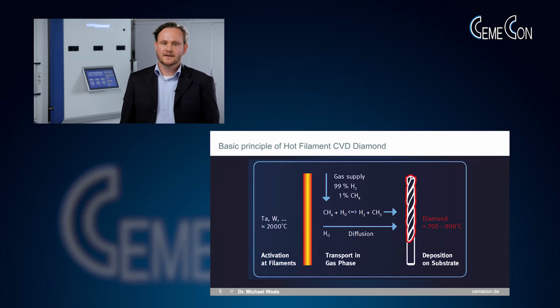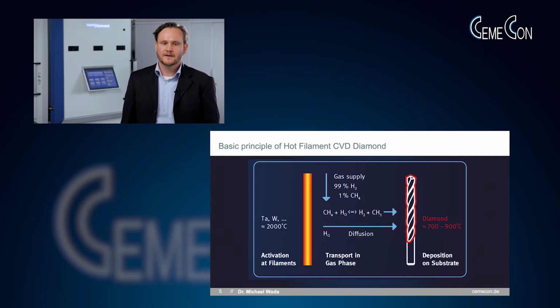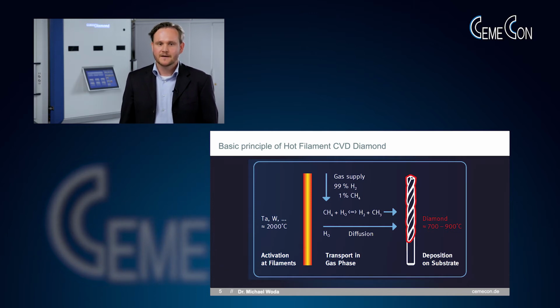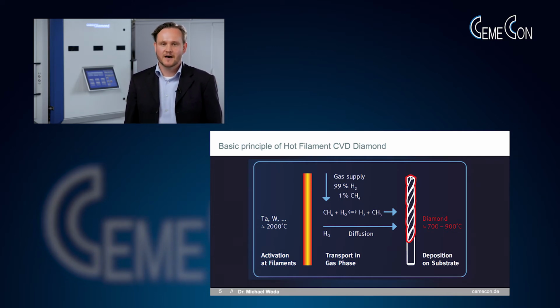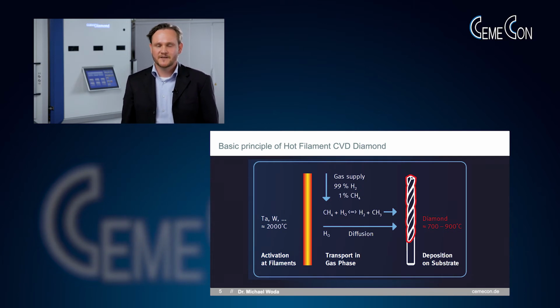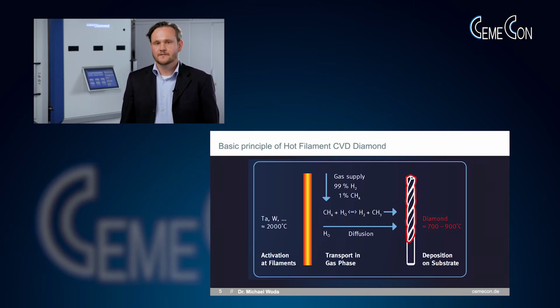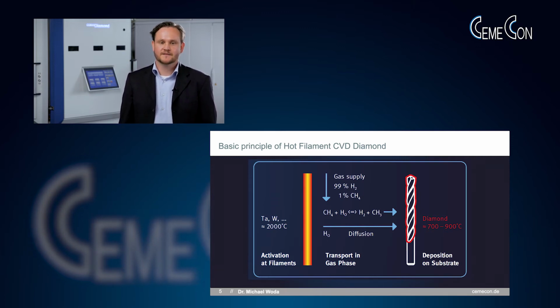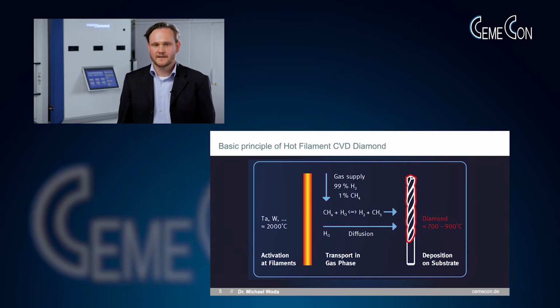This atomic hydrogen can reduce the introduced CH4 methane to a CH3 methyl radical. Further on, another contribution of the hydrogen can generate free surface places on top of the substrate via etching. The dangling bond of the CH3 methyl radical can attach to another free carbon bond on top of the surface. This can either be a diamond seed in the starting phase of the process or the growing sp3 network later on. The substrate, which is our cutting tool on the right-hand side, deserves some extra attention I want to address on the next slide.